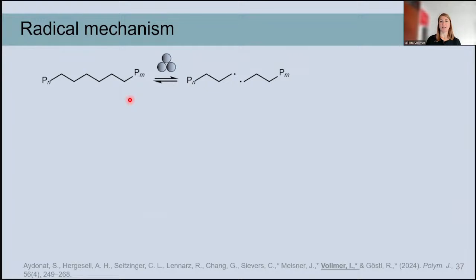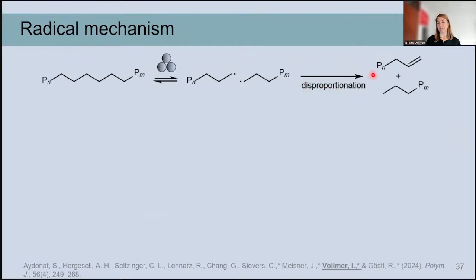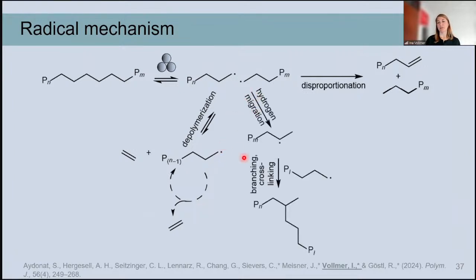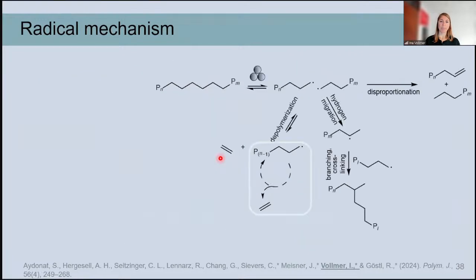So we have the homolytic carbon-carbon bond cleavage generating two radicals, and these can either terminate by recombining back and just reforming the polymer, or they can disproportionate by forming a saturated and an unsaturated bond. But what we really want, of course, is the depolymerization, which creates a monomer and also regenerates the radical. There are also some other reactions that can happen, but we are focusing on the depolymerization here, of course.